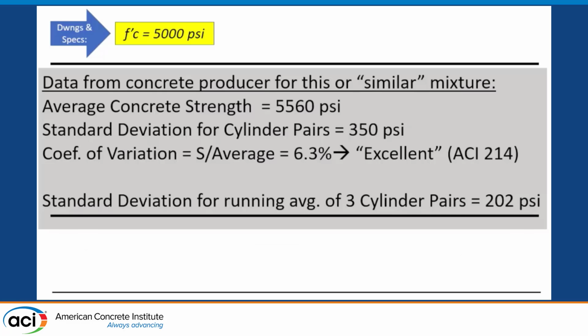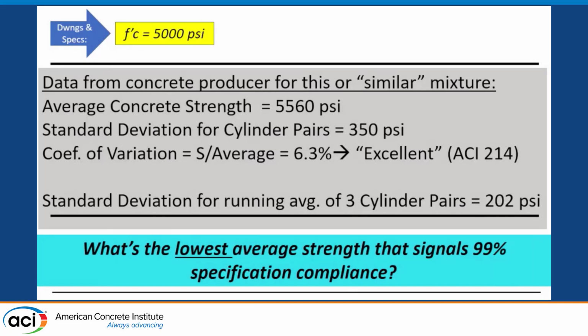Okay, so we get data from the producer. We got an average concrete strength of 5560. We got a standard deviation of 350. That's a coefficient of variation of 6.3%, which ACI 214 would say is excellent. This is excellent quality control. When we do the standard deviation for the 3-cylinder pairs, that's 202. Now, what's the lowest average strength that would signal 99% specification compliance?